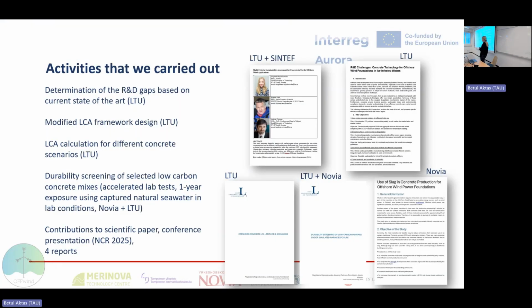So within the project, we did several different activities. So we determined the R&D gaps based on the current state of the art. We established a modified, simplified LCA framework to be able to include durability and perform calculations for different types of concrete. We also did some lab tests for the durability screening of selected low carbon concrete mixes, taking into account accelerated lab tests and also lab tests with natural seawater captured in the Gulf of Bothnia.